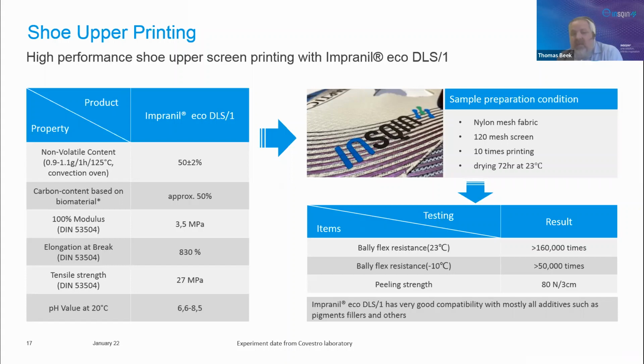For this printing, we had to use a 100% nylon mesh fabric and a 120 mesh printing screen, and print 10 layers with a short intermediate drying by a hot air dryer, and a final drying step at room temperature for 3 days. We could achieve very good Bally flex resistance of more than 160,000 turns at 23 degrees, and also more than 50,000 turns at -10 degrees. We also have a very good peeling strength of 80 Newton per 3 centimeters.